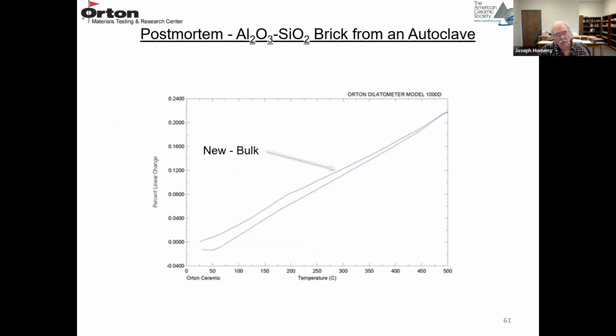So I mentioned using thermal expansion traces to try to isolate maybe a maximum use temperature. This is percent linear change again versus temperature. This one only goes up to 500 degrees C. And this trace was run on a new material. So it goes up pretty linear and comes back down. There's a little offset, but nothing really is happening on the new material. It's reversible thermal expansion.